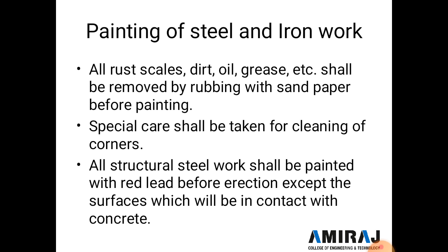Now the next important point is the painting of steel and iron work. All the rust, scale, dirt, oil, grease, etc. shall be removed by rubbing with sandpaper before painting, and special care shall be taken for cleaning corners, and all structural steelwork shall be painted with red lead before erection, except the surface which will be in contact with concrete.